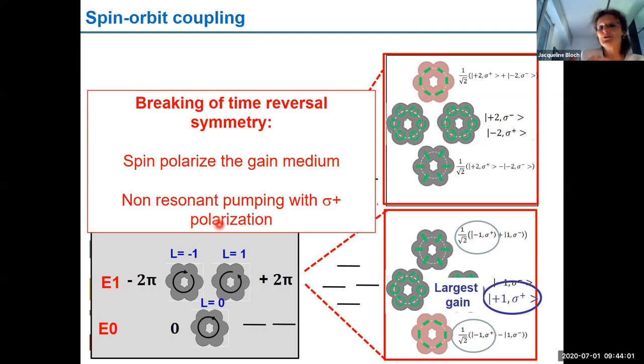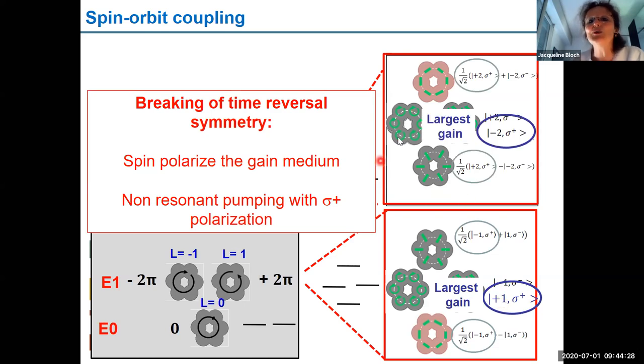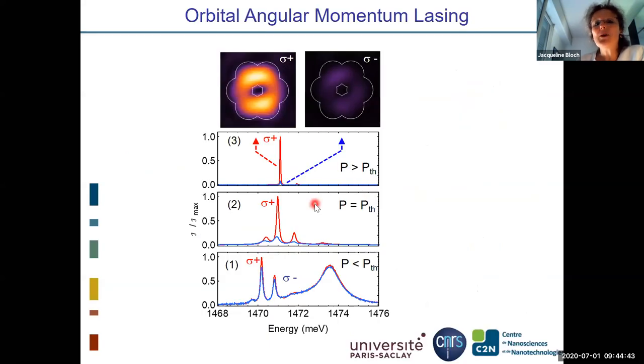And then when you reach transparency, there will be mode competition between the different modes. The modes which will couple to a sigma plus polarized gain will be these three modes because they have a sigma plus component. But you see that because of this one over square root of two, these two modes will have a coupling which is twice smaller than this one. So this one will win the gain. And it's the same if you tune the gain to the other manifold: you have a chance to see lasing in this mode, which is sigma plus, and then you will see L equal minus 2. So this is what we want to do: break time reversal symmetry with the polarization of the pump.